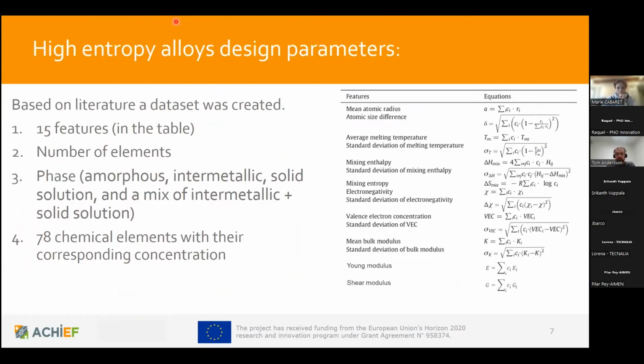So the database for this neural network is based on literature survey. And for these different traditional features or traditional high entropy alloy design rules, meaning mainly this mean atomic radius, average melting temperature, mixing enthalpy, electronegativity, and valence electron concentration, and mean bulk modulus, and the standard deviation of those, and also this mixing entropy and Young's and shear moduli are used here. So these parameters are searched from the literature for different alloys, and then used to form this kind of a database to